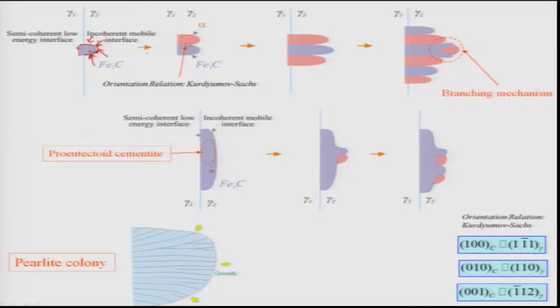This leads to a huge reduction of the carbon concentration in nearby regions, and therefore this allows nucleation of the alpha, because alpha requires almost no carbon. As I told you, at 727 degrees Celsius the carbon concentration of alpha is about 0.02 weight percentage, and at room temperature it has no carbon. So because of that it can nucleate very easily on both sides of the Fe3C and grow in the same direction, as you see here in this direction, correct.